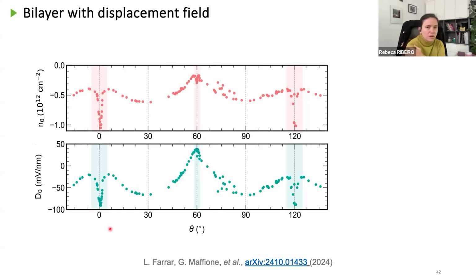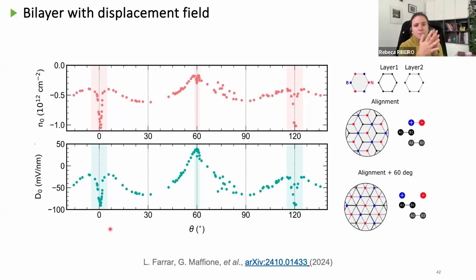And the reason why these two are changing, as you might expect so far, is because of the carbon and boron nitride atoms and how they arrange with respect to the bilayer graphene. So for example, here we have the lattice structure of bilayer graphene. This is layer 1, this is layer 2, layer 1 is on top, layer 2 is on the bottom. In bilayer graphene, what really matters to have a displacement field is the difference in electric field felt between, or that you can find between, A1 and B2 atoms, okay?